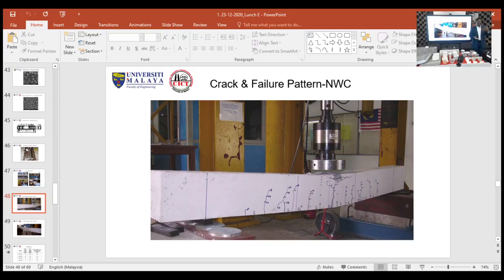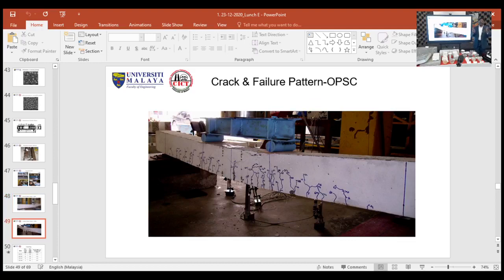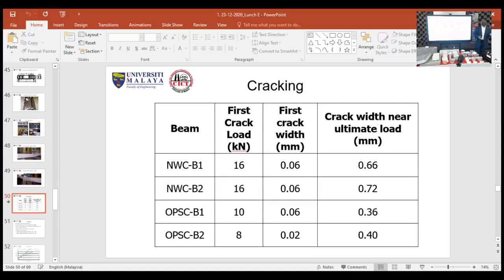So this led us to understand that this has a lot of ductility ability. It has a ductile ability to absorb the load, and you can see the crack width in the normal weight concrete, it's 0.66 at the ultimate load, whereas in the lightweight, because the number of cracks is more, the width of the crack is less. So that's what we see here.